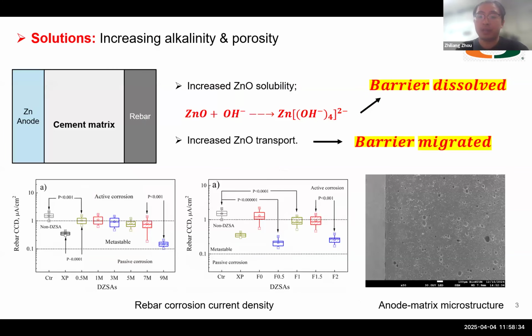To solve this problem, some past studies proposed two methods. One is to increase the pH value of the electrolytes near the sacrificial anodes, which can increase the solubility of anodic products. You can see these reaction equations: the zinc oxide reacts with hydroxide and becomes complex ions. So the formed solid-state barriers can be dissolved as ions. The other method is to increase the porosity of the cement-based matrix, because higher porosity can not only reduce the ionic resistivity, but also provide enough space for the barrier storage.